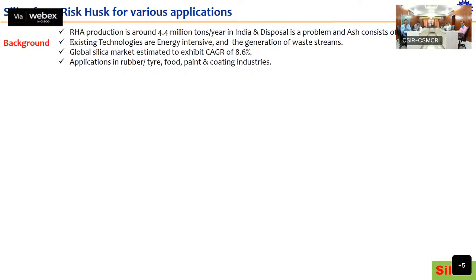One is to make precipitated silica from abundantly available rice husk. As India is one of the farming countries, we majorly grow rice, and rice husk is produced at about 4 million tons per year. But the problem is that rice husk has disposal problems. We have to burn it, and during this burning we generate a lot of carbon dioxide and environmental concerns. And that ash consists of about 75 to 90% silica.